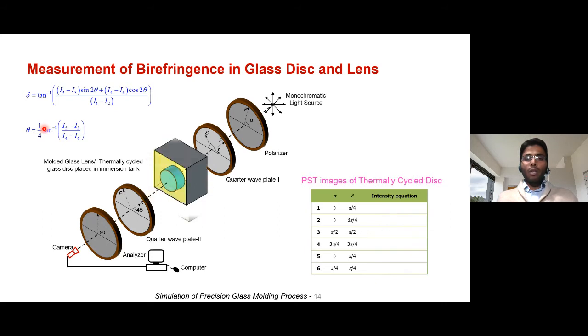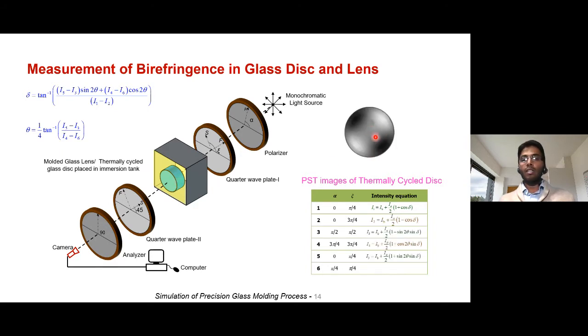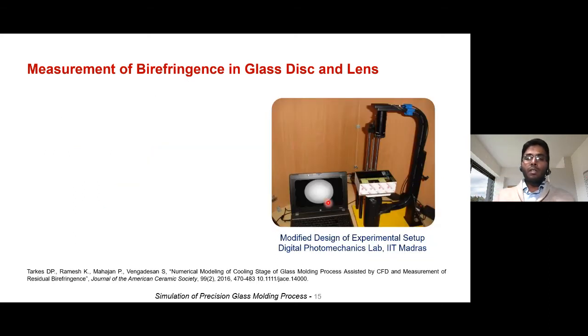And then we performed experiments on the thermal glass disc. Similarly, we took 6 phase shifted images, and you can see that since the glass disc has very high residual stresses, you can clearly see a gradient of fringes. And for performing all these experiments, we had a customized experimental setup at IIT Madras. So this is the polariscope that we have. We have the incoming light source over here, and we have the camera to capture the images. The lens was placed in the refractive index matching liquid, and then all the photoelastic experiments were done.